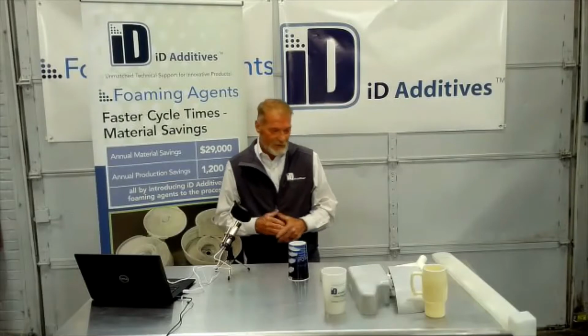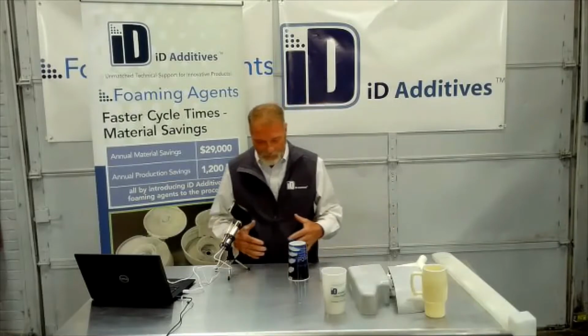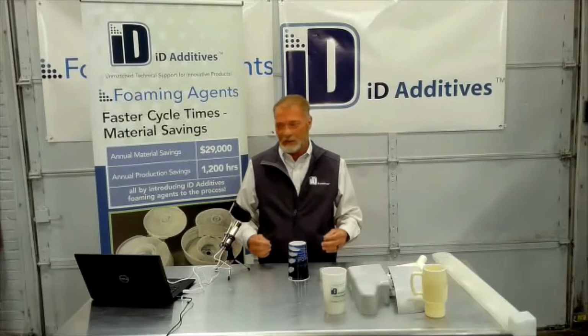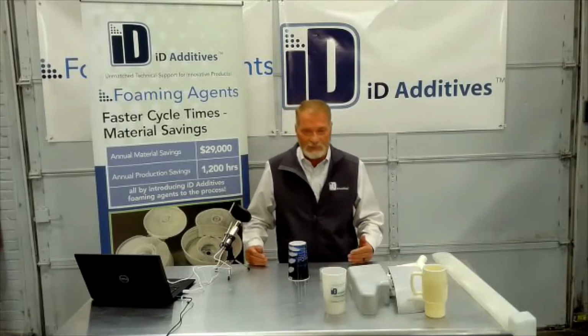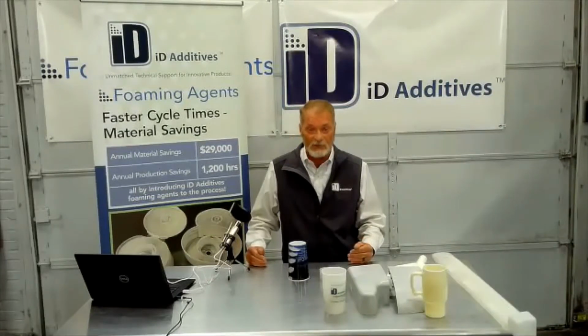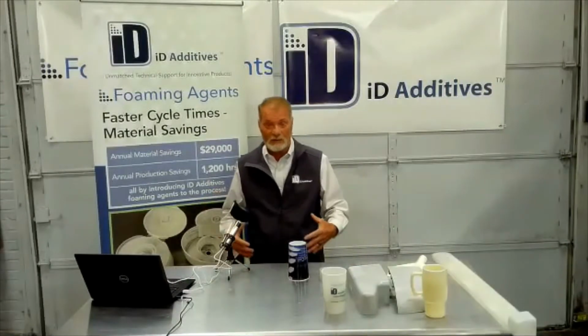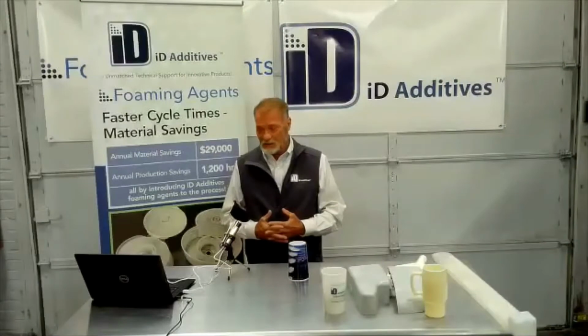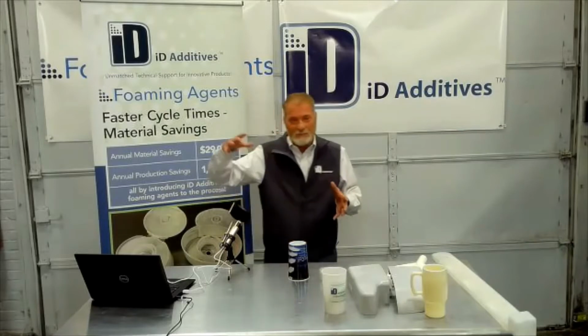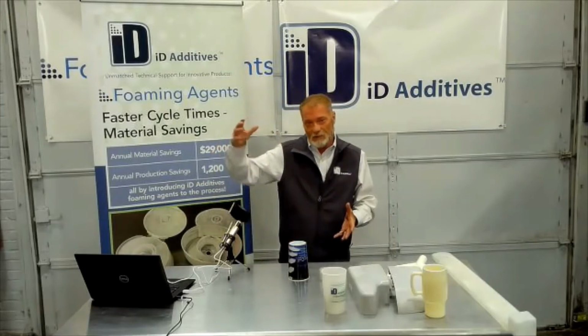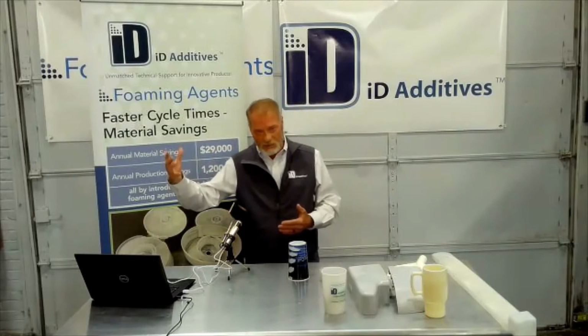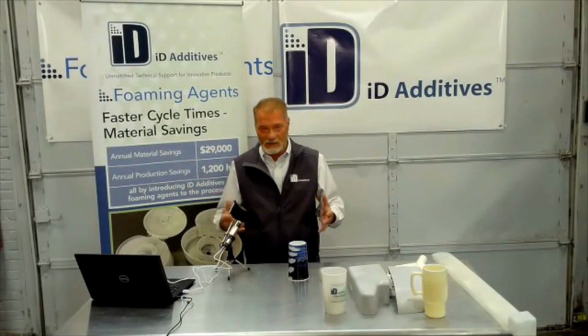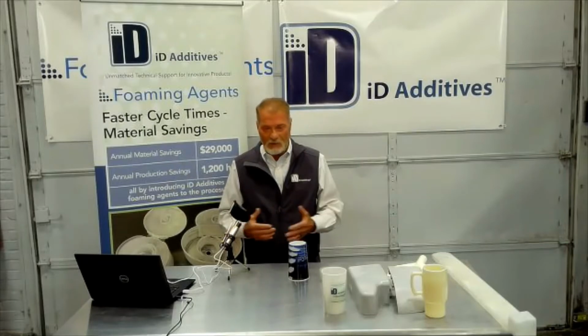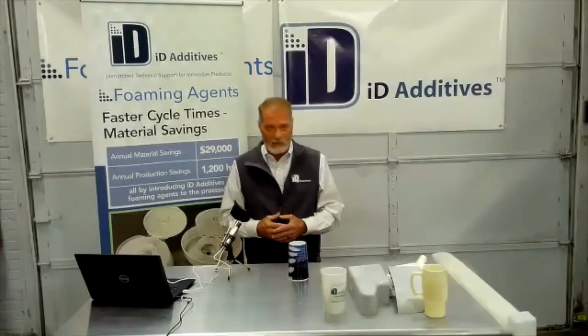Some parts, because of splay, because of the machine, maybe not all parts are a good fit for a foaming agent. That's why we would recommend a filler like calcium or talc, just a filler to pull out some of that polymer. But the combination of the two makes great nucleating sites for the foam, and the cell structure is much smaller. When you add that 10%, your weights go up. But if you add foam with it, you can actually pull the weights back down and still get a stiffer, more rigid part, and the cell structure is amazing with calcium.